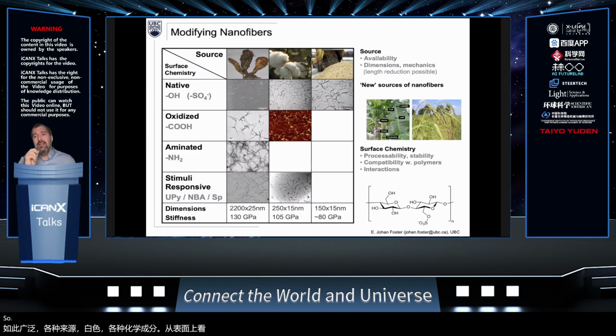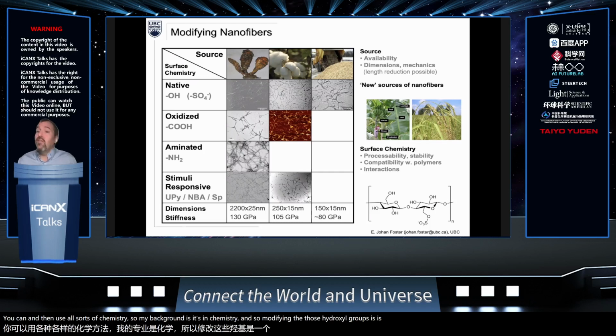So the cellulose nanocrystal, as the name suggests, is made out of cellulose. So that repeat unit that you see in the bottom right, it's a lot of hydroxyl groups. We can put a few charges on the surface depending on how we make that material. So sulfate groups, for example, if you used sulfuric acid to dissolve away the rest of the tree, you could put phosphate groups on the surface, which I'll talk about a little bit later. You can hydrolyze the primary alcohol to a carboxylic acid. You can, and then use all sorts of chemistry. So my background is in chemistry, and so modifying those hydroxyl groups is always very fun, because that allows us to do all sorts of tricks with these.